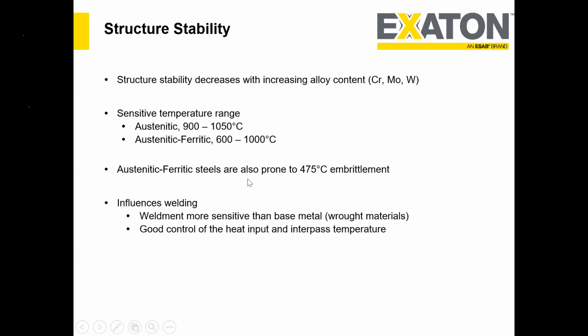Another important thing is that austenitic-ferritic stainless steel is also prone to 475 embrittlement. This 475 embrittlement is very critical, and I get a lot of questions specifically about post-weld heat treatment. We'll explain later why it is challenging to do a conventional post-weld heat treatment, even in a cladding, let's say duplex cladding on carbon steel. Why can we not do post-weld heat treatment or stress relieving at, let's say, 600 or 610 degrees centigrade? This is one of the culprits.